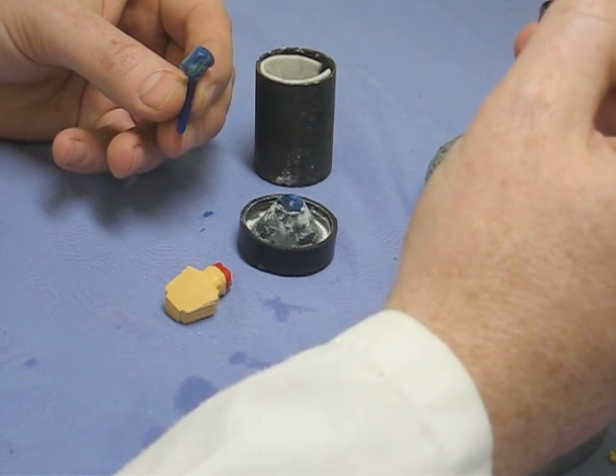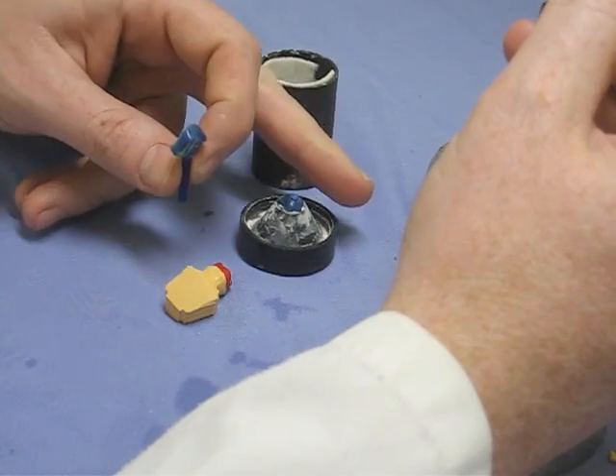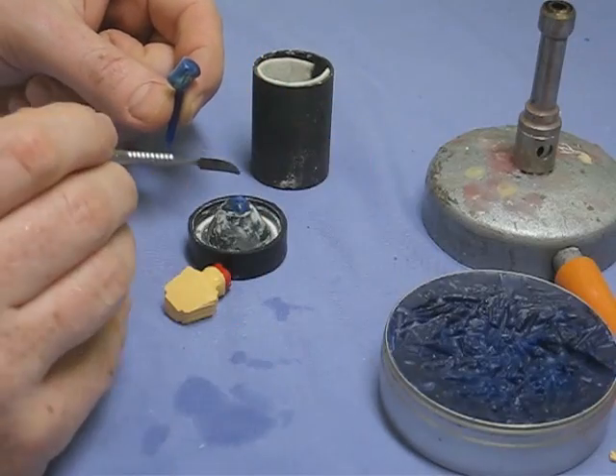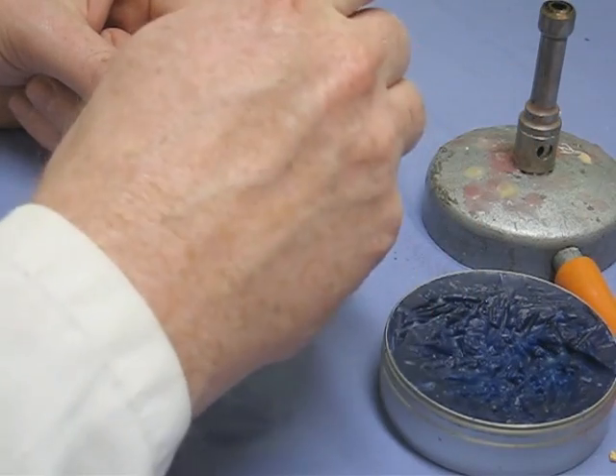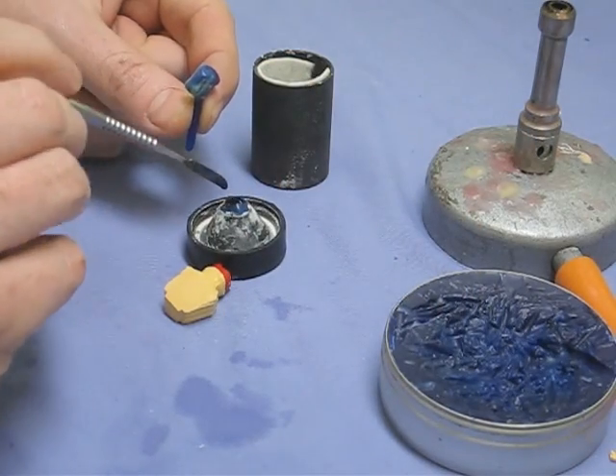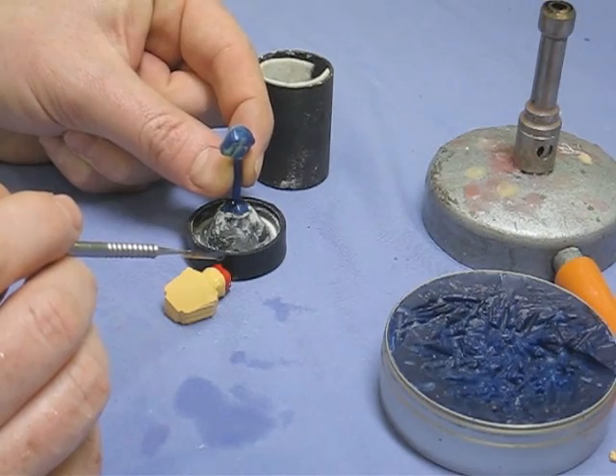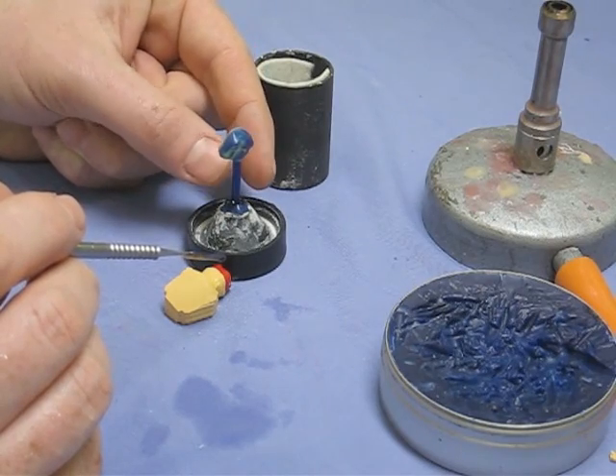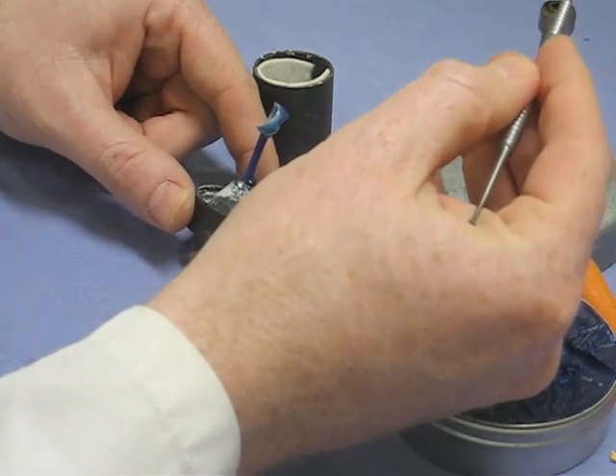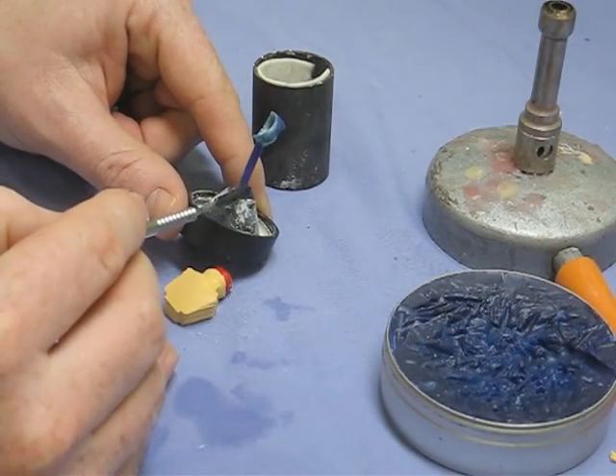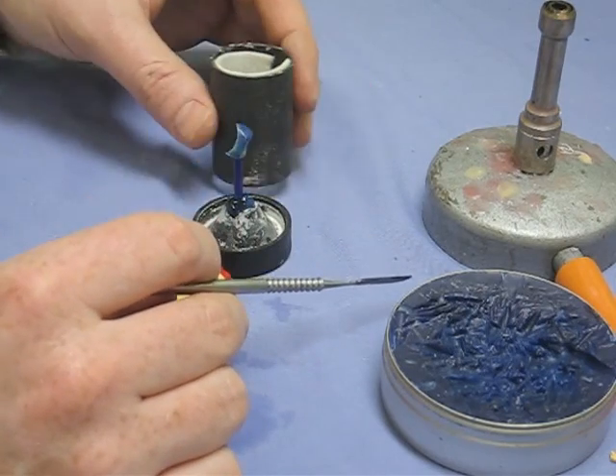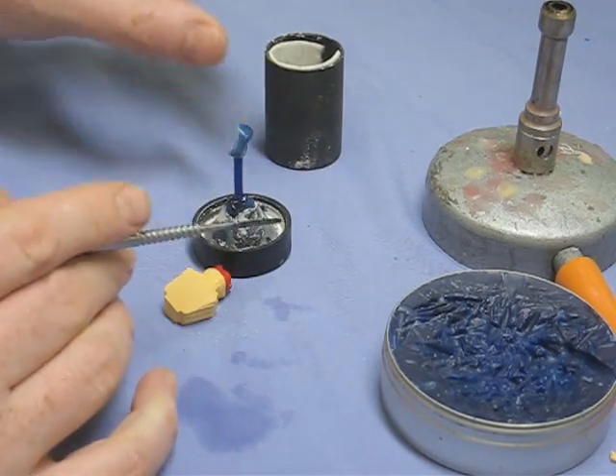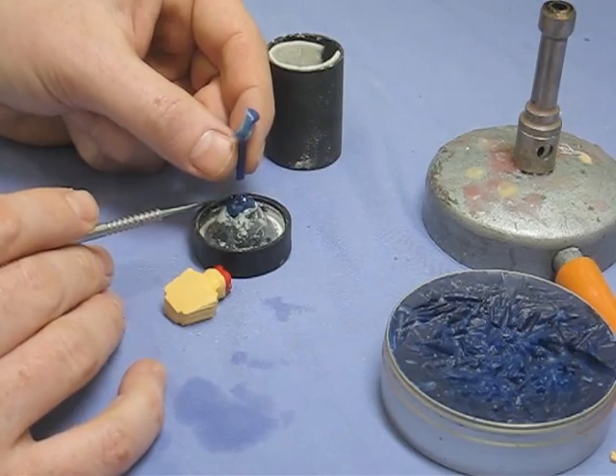So the pattern's made, invested, the whole lot's expanded by us heating it up and then the metal's shot in and then the whole lot shrinks down to the original size together. So we have to get the match between the two materials correct. This has been worked out over many years and is accurate to many parts per million these days. Gold and Cristobalite tend to be the best match so that's why they're more favourable.